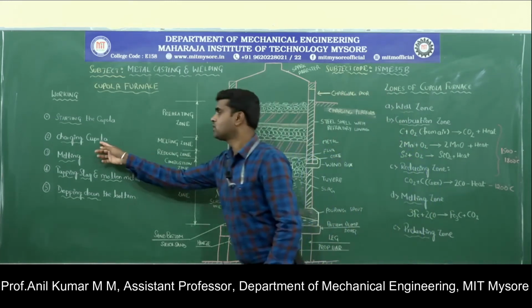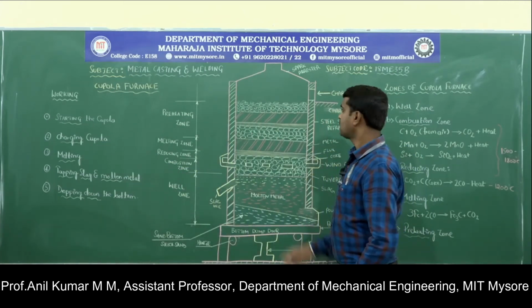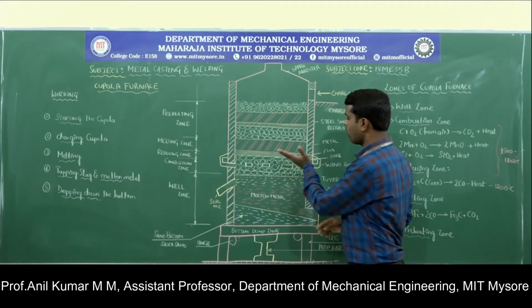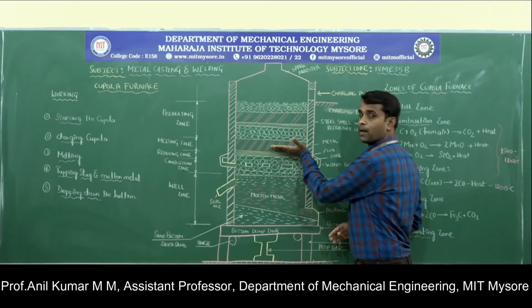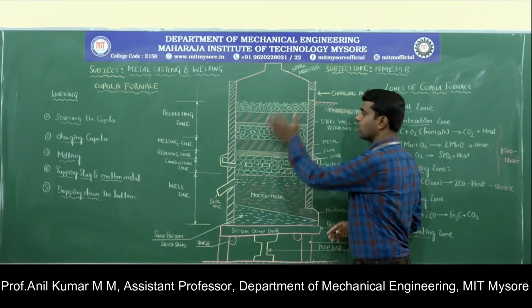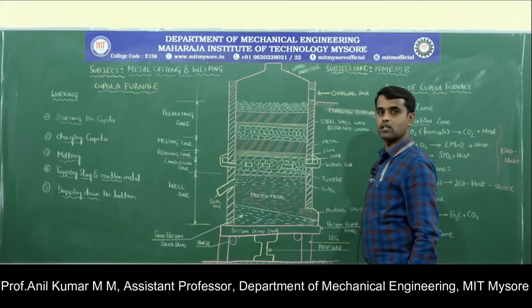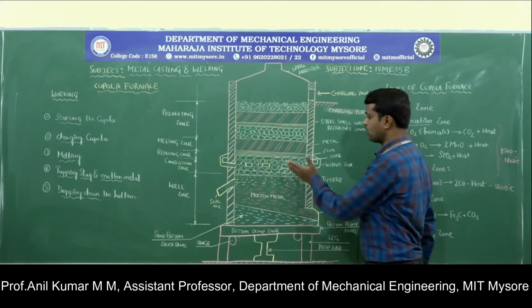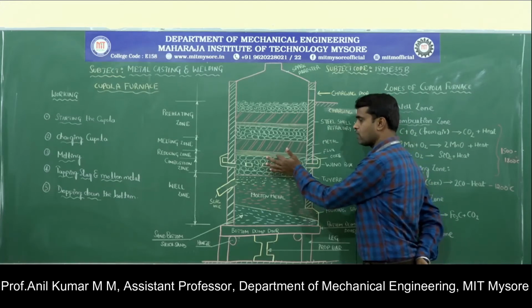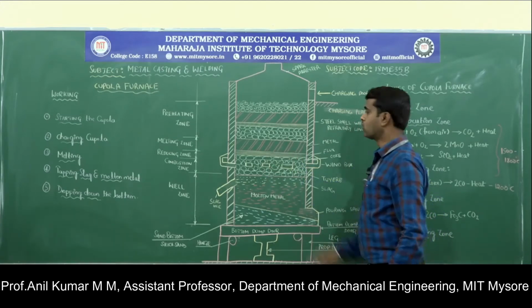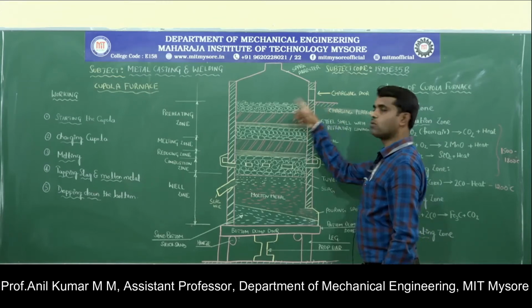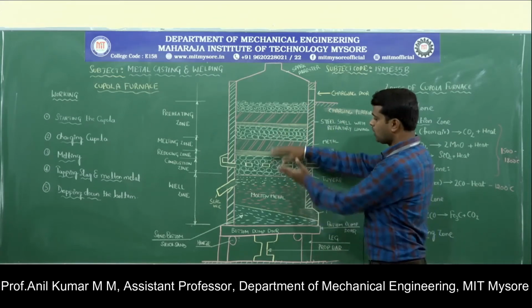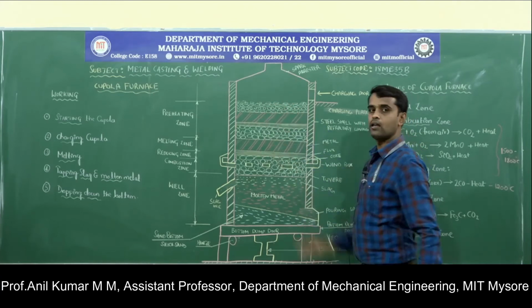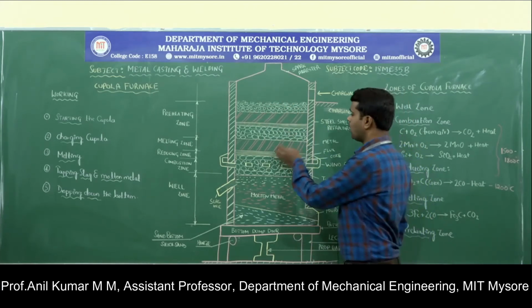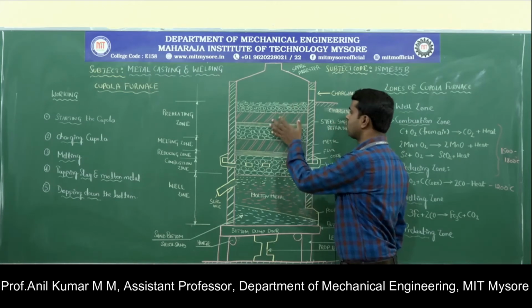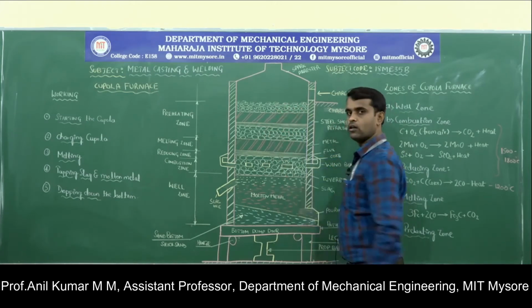Next step is the charging of the cupola. The charging consists of alternative layers of coke, flux, and then the metal, that is iron, which will be added inside the furnace through the charging door. So the charge consists of coke, flux, and metal. This charge will be added continuously through the charging door into the furnace.